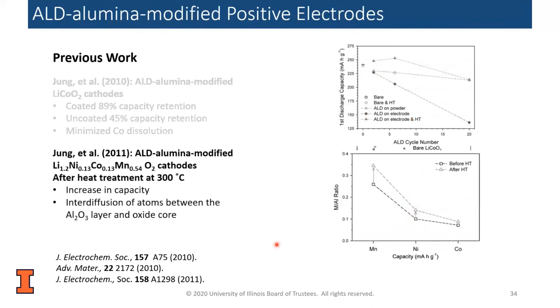Then another group studied NCM material, and they also noticed an increase in the capacity. But then they also noticed that after heating, there's some interdiffusion between the atoms in the alumina layer. That is, it looked like both the manganese, nickel, and the cobalt signals were all increasing after the high temperature treatment. So it looked like the material, the metal oxides, the transition metal oxides that actually are reactive and prone to dissolution will eventually move back to the surface.